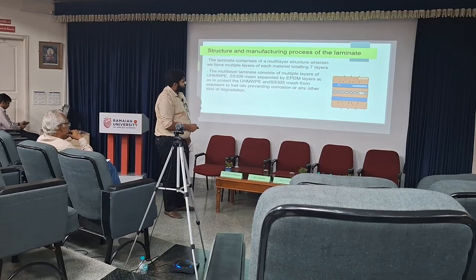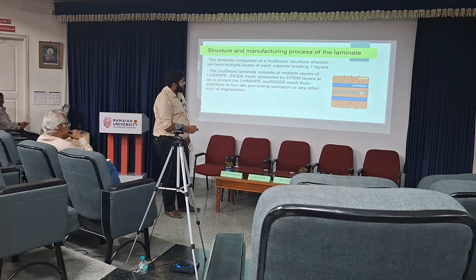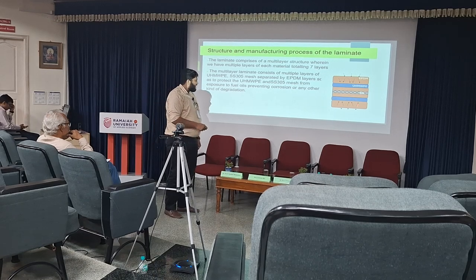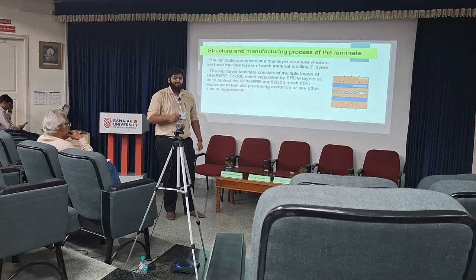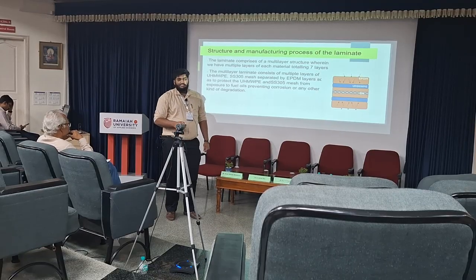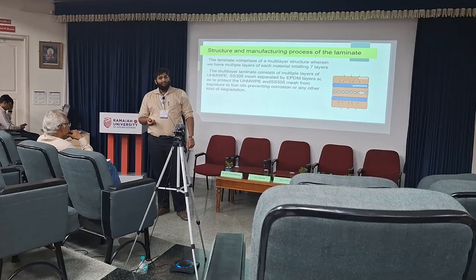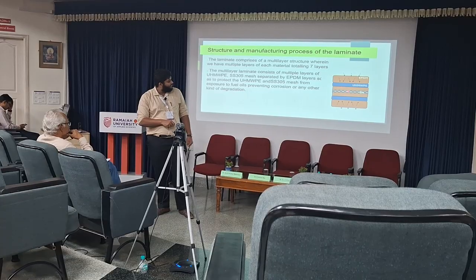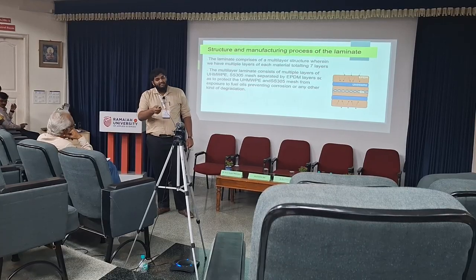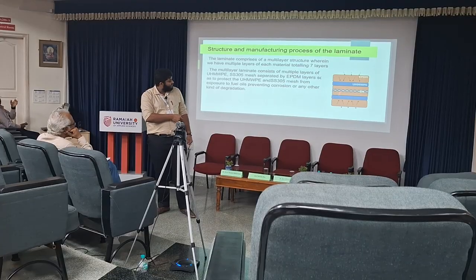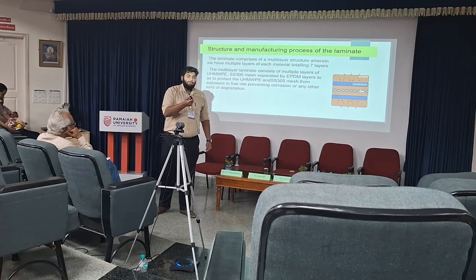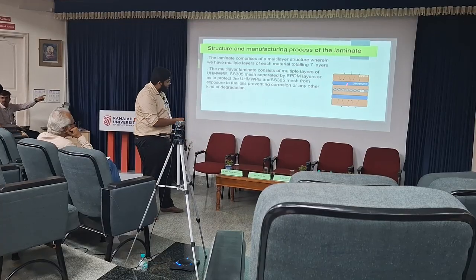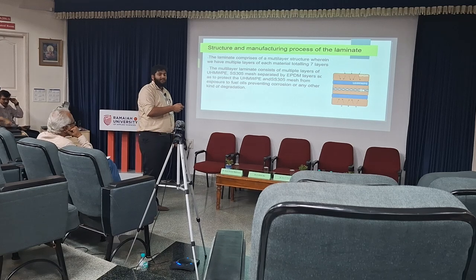You see EPDM, then we have a layer of UHMWP, again EPDM, this is the stainless steel mesh, again EPDM, UHMWP, and then again EPDM. So why so many layers of EPDM? Because as I said, UHMWP or stainless steel might not handle the corrosion due to fuel oils that well, but EPDM is very good at it. So here we have laminated EPDM and tried to isolate each and every layer, which helps us in protecting these layers from the fuel oils. So that is why we have such multiple layers, isolating each and every layer of alternate material.